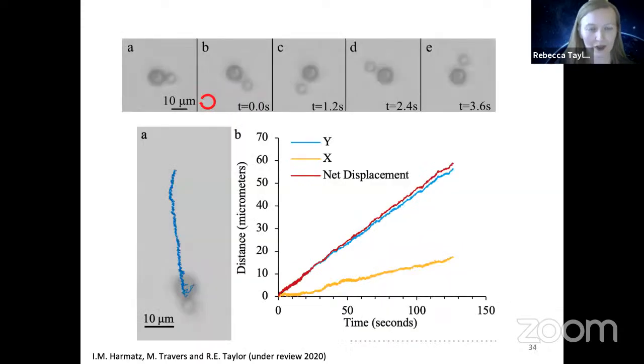So this is a demonstration not only that it's swimming, but that we built an elastic connector between the 2. To back that up and give you more information, when we rotate this in place, we see that the beads unfold, or stretch that elastic element between them if you're just doing a rotating magnetic field. But once you start doing your oscillating magnetic field, they pull back together and then scoot off with a known velocity. The separation when they're apart, I should say, matches the separation they had in the template. So this is a demonstration that we can control the mechanics and the structural dimensions of elastic connections, enabling complex body plans in micro robots.